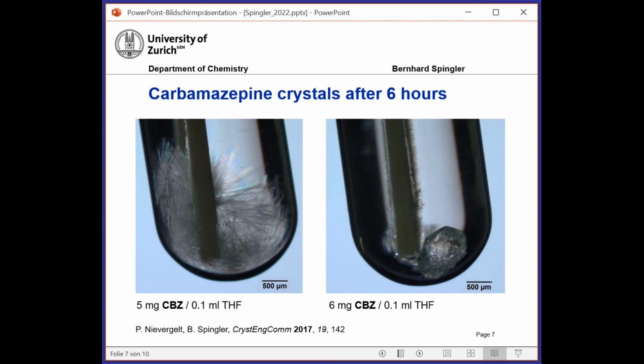CBZ crystallizes in different polymorphs, and you can already see here by eye that we crystallized two different polymorphs. One is a very fine needle-like polymorph, the other one is a rather massive three-dimensional crystal. And then we were curious about the crystal quality, because you see in the title that these crystals were grown relatively fast, within only 6 hours. And you hear quite often that for a good crystal, this needs to take a long time. Well, at least for this system, this was clearly not the case.